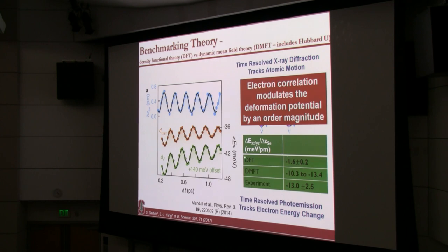it turns out there are two computational results and an experiment. Even better, the theory was done by the Rutgers group before the experiment, so we at least have things on the record on this important physical quantity, the deformation potential. They differ by an order of magnitude. People tried to resolve them, but the error bar in previous experiments was bigger than the difference of the predictions. But now you can have an experiment which is much closer to this so-called dynamic mean field theory. In this particular case, the Hubbard U was included in the calculation, which I will come back to. It's not a single Hubbard model, but the spirit of the Coulomb interaction was included